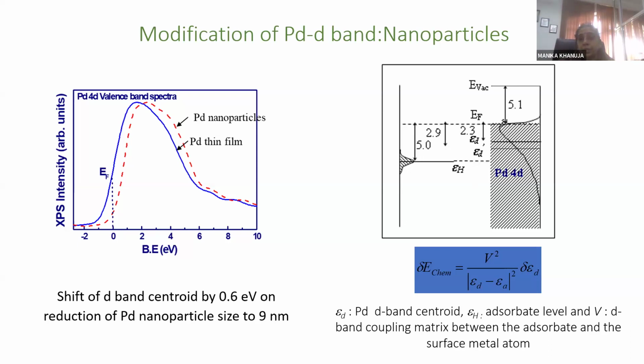To achieve this good electronic compatibility, or to enhance it, nanomaterials are there. So in these palladium nanomaterials, we have this orbital shift. Hydrogen is fixed at 1s, which is 5 electron volts below the Fermi level. By making nanoparticles, we are shifting it from 2.3 to 2.9. If my maxima shifts from 2.3 to 2.9, it means the electronic compatibility is there, and the chemisorption or physisorption phenomena taking place during gas adsorption will be significantly improved. So we formed the nanoparticles and confirmed it through scanning tunneling micrographs. Then through XPS we see the shift in the Fermi level, and the further enhancement in sensing properties we confirm directly in application. This is how the whole picture comes.